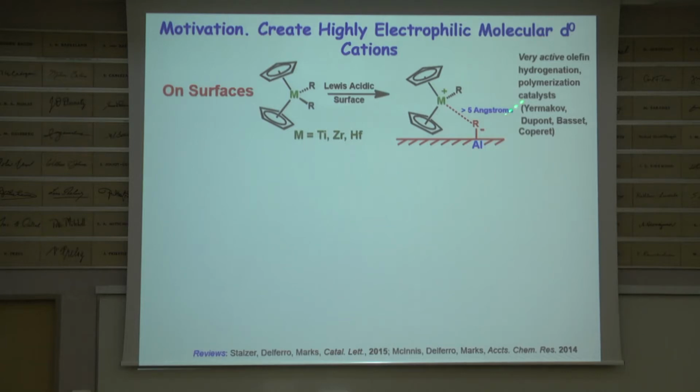This is absolute nonsense. But the counter to that is, what else is going to give you a 10 to the 7th-fold enhancement in, say, olefin hydrogenation activity, comparable to platinum metal catalysts? And so what we could see from the NMR was that this became much more electron deficient. These are solid-state C13 measurements. We put a paramagnetic probe here. We could see that this distance was greater than 5 angstroms. Now, in response to the criticism, we said, aha, I'm an organometallic chemist.